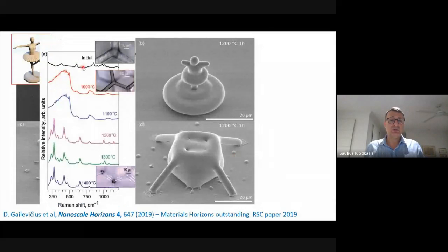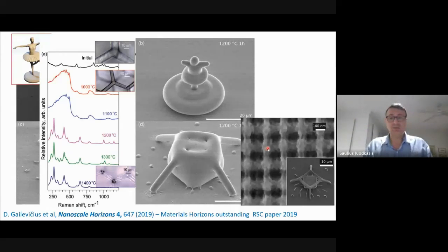After annealing at high temperature, you can recognize Raman spectra of glasses, typical glass. You see the glass a little bit dark because carbon should be burnt and it's coming out of your microstructure. But if you continue with the conditions, time and temperature, you can begin to have material which has different crystalline phases. You can recognize them. It's cristobalite in this case, also some zirconia oxide crystalline phases are created depending on the temperature. This is also simply to show the capability. There is no easy way how to fabricate this, and this is one of the possibilities.